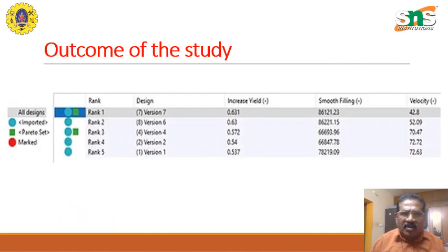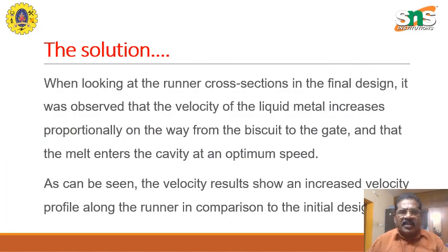Okay, so moving on, the outcome of the study shows that there is an increased yield, a smooth filling, and the velocity of the flow was also much better. Now, when looking at the runner cross sections in the final design, it was observed that the velocity of the liquid metal increases proportionately on the way from the biscuit to the gate, and that the melt enters the cavity at a very optimum speed. And we can see the velocity results show an increase in velocity, which I just showed previously, and the velocity profile along the runner in comparison to the initial design.